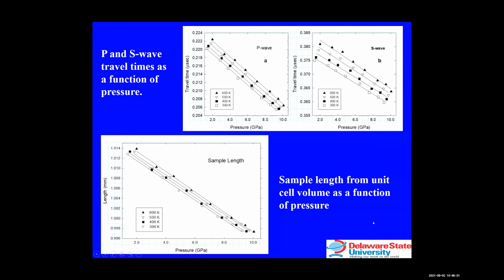Again, in this diagram, I showed the plot of the P and S wave as a function of pressure. You see that the travel times decrease linearly and systematically with pressure, and also the length of the sample shown on the lower left corner.